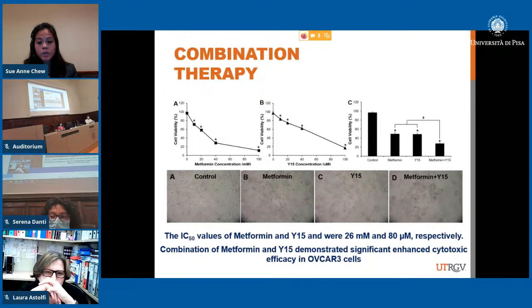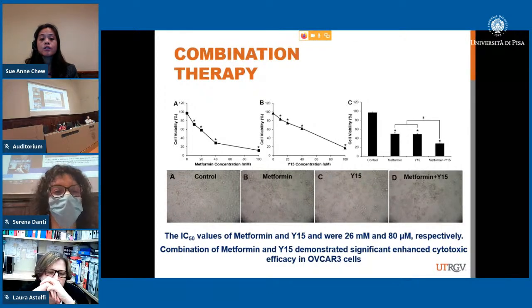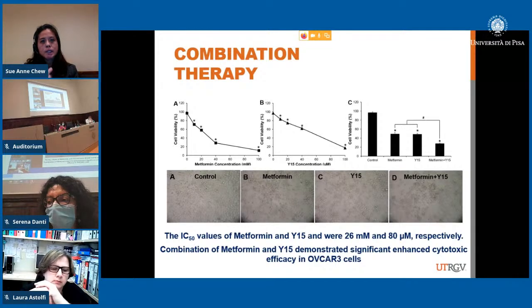These are OVCAR3 cells, and we saw that the IC50 for metformin was around 26 millimolar, I would say pretty high. And then for Y15, it's more sensitive. It's 80 micromolar. I think it's expected. Metformin is an anti-diabetic drug, right? So you expect that for it to function as a cancer drug, it has to be used at a pretty high concentration. So it can be a challenge sometimes to get to that concentration to have that effect.